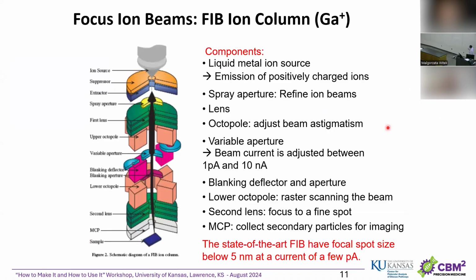Okay, so in order to understand what parameters you have to control to produce the structure you want to build with FIB, I don't want to go into detail, but I think it's good to understand the basic structure of the ion column. It's a very complicated system. But if you see here, you have the ion source, where the gallium or xenon ions are produced from the liquid ion source. Then you have the extractor, where you apply high voltage so that you direct those produced ions towards the sample.